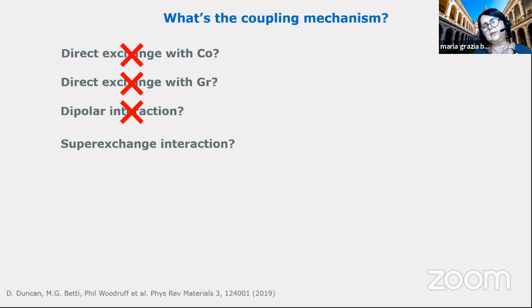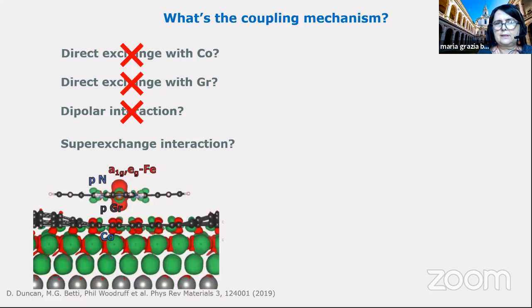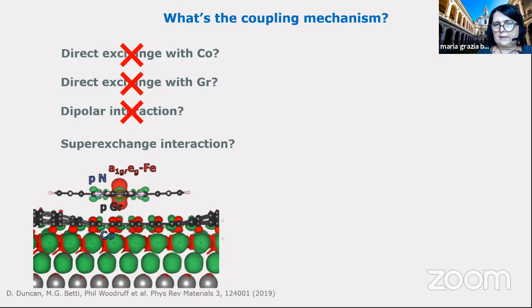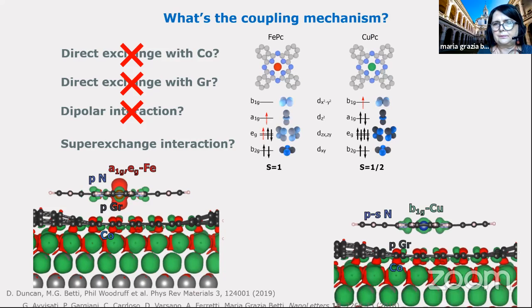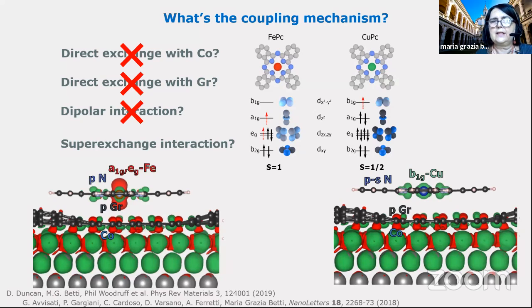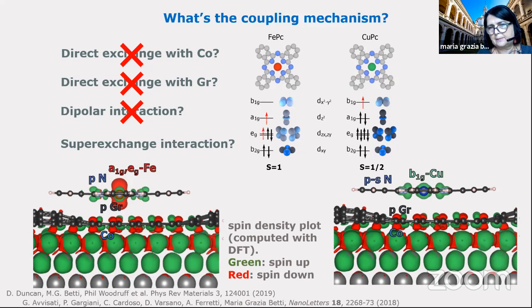So another hypothesis is that we can have a superexchange interaction. This is an interaction that was proposed by Mott for transition metal oxides or for other systems like this. And then we tried, with density functional calculations of the spin density of this system, to understand if this is a good hypothesis. These are spin charge density plots computed with DFT. You can see the green is the spin up, the red is the spin down. This is cobalt, this is graphene, this is the molecule. So now you have a green spin up here and red spin down here.